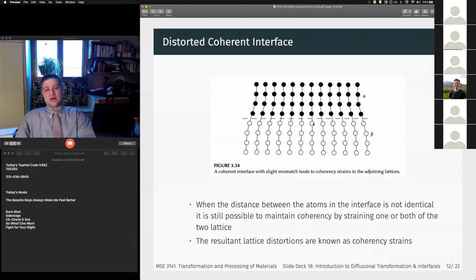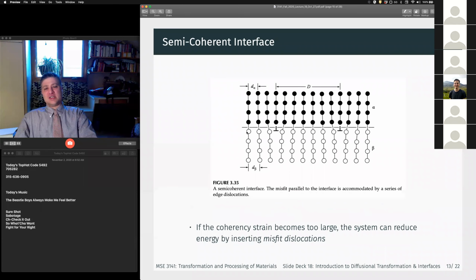So a coherent interface, if the correspondence is close, can still be maintained, right? But obviously, what happens if this gets too large? What happens when the atoms, in order to maintain this coherency, end up being squished too much, right? Then we get what is called a semi-coherent interface, where edge dislocations pop into being to relieve some of these strains, right? When the energy cost to create a dislocation becomes less than the energy cost to maintain the coherency strain, then we get a semi-coherent interface where edge dislocations pop into existence.